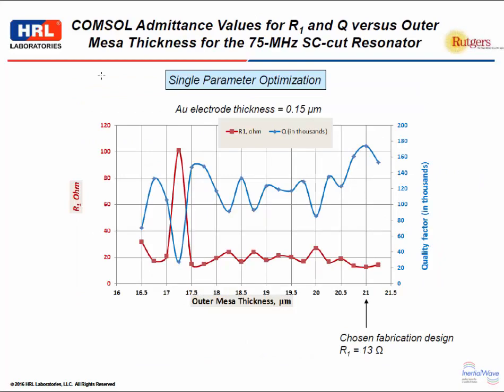And we did the admittance optimization. This is just single parameter optimization. You can do multi-parameter optimization within our COMSOL models by varying the outer MESA, the designs of the electrodes, the configuration of the electrodes, etc. We just looked at one parameter, which was the outer MESA thickness, and varied that. And we chose one, as I mentioned, around 21 microns, which gave us an R1 of around 13 ohms and a predicted Q of over 100,000. And this was, by the way, for a 75 megahertz SC-cut design.